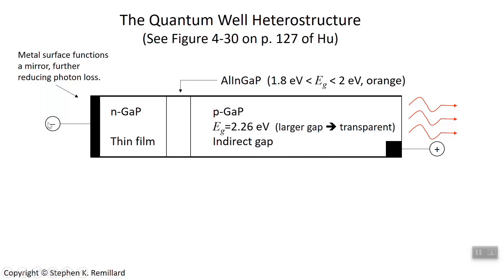We put these bias terminals on the metallic pads. The n-type is biased negative and the p-type, which has this tiny little pad, is biased positive. The reason for the tiny little pad is to leave room for the light to get out. Bias negative on the n-side and positive on the p-side is forward bias. There is a band structure that we need to consider when you put these three semiconductors together. Before you turn on the bias voltage, you can estimate what the band structure would look like, given that the Fermi energy is flat for an unbiased semiconductor.